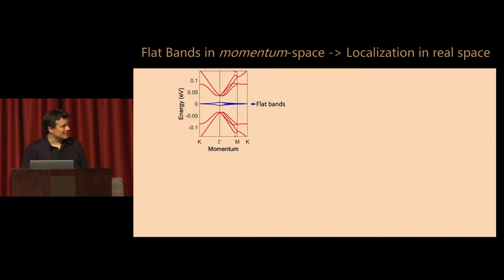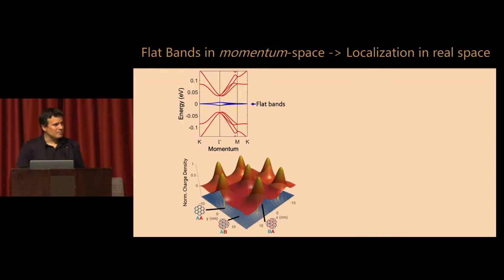Those flat bands, you can see here, the blue band is the flat bands. Red ones are other bands which are higher in energy that we don't care about for now. But a flat object in momentum space, remember this label, momentum space, if you want to go to real space, you have to do something called a Fourier transform, a mathematical Fourier transform. And the Fourier transform of a very extended object is a highly peaked object, which means that when you put electrons in magic angle twisted bilayer graphene, they like to sit in certain regions of your moiré pattern. You can see this distribution is highly peaked in certain regions and not in others.